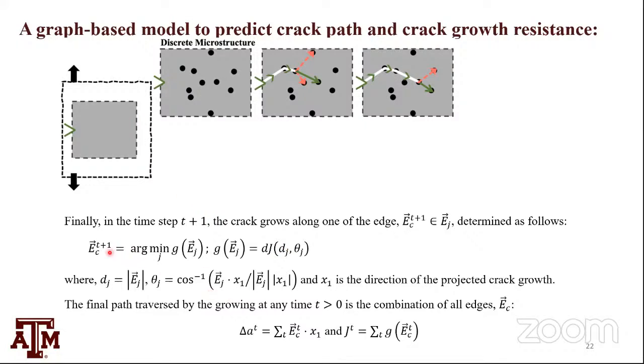And once I know all these ECs at every time step, I can simply sum up their projection, and that gives me my projected crack length, what we measure in experiments or rely on for ASTM analysis. Once I have all these unit events of these G's, I can sum total of them, and that will be my J at any given time T.